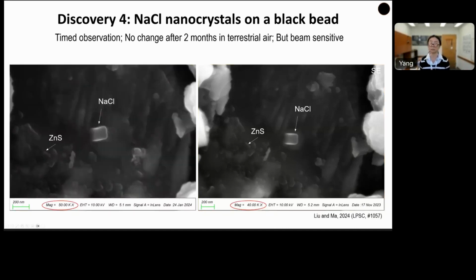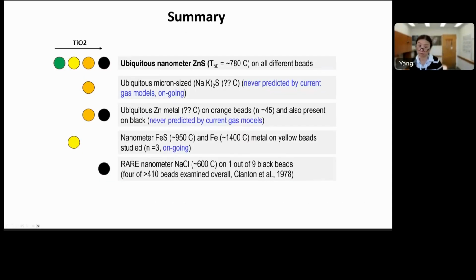As most of you know, sodium chloride under electron beam may not be stable, so we also timed our observation. We prepared the sample and conducted the observation within 30 minutes. We came back to look at the sample 7 hours later. Nothing changed. Then we checked again 2 months later. As you can see from the dates here, it's about 2 months later, and the sodium chloride is still there, but it is very beam sensitive. Sorry, the magnification here is slightly different, but the shape and size of the sodium chloride didn't change over 2 months.